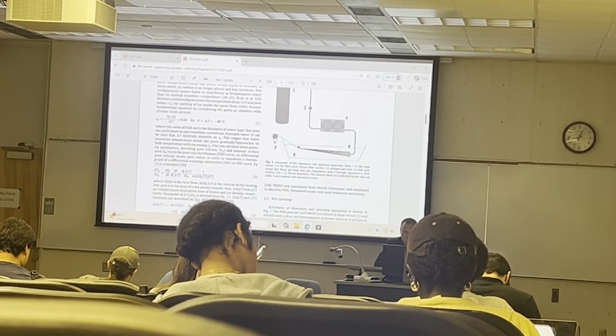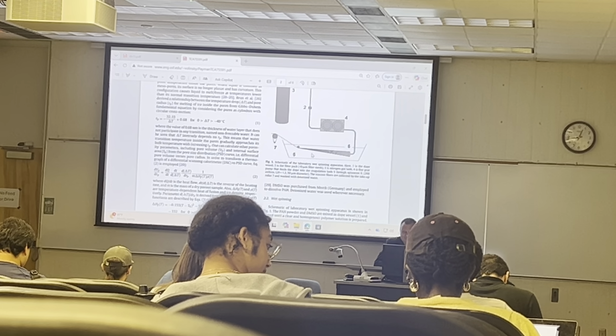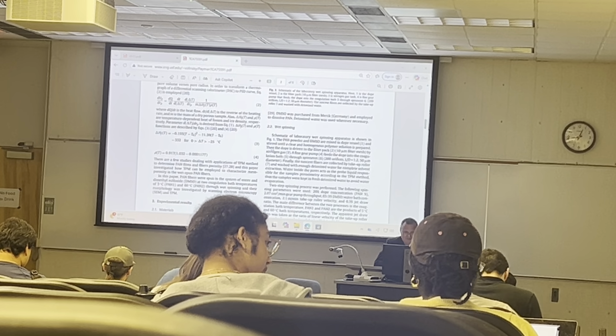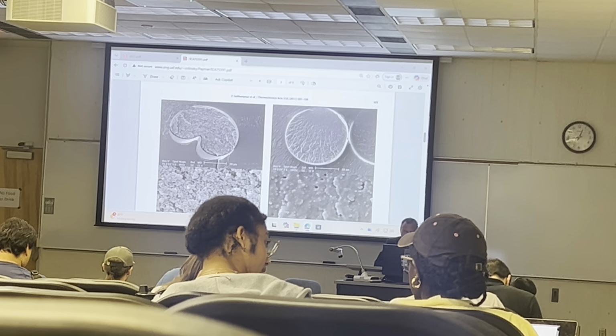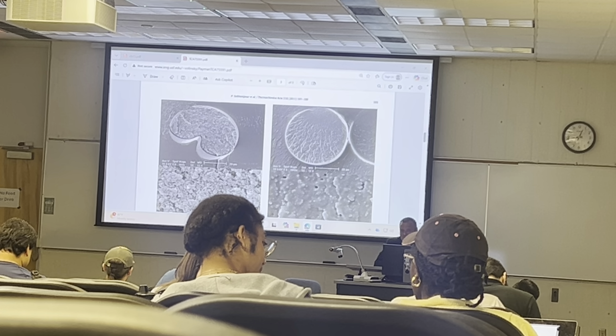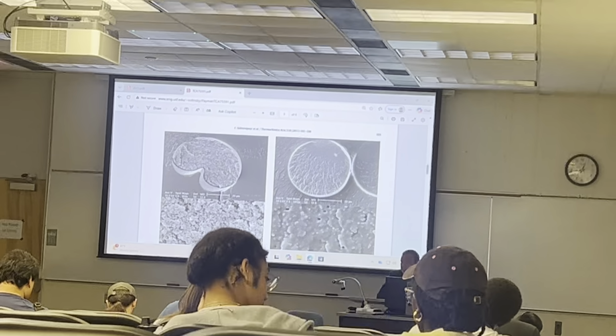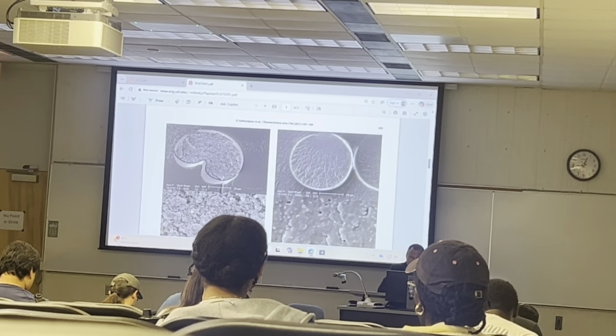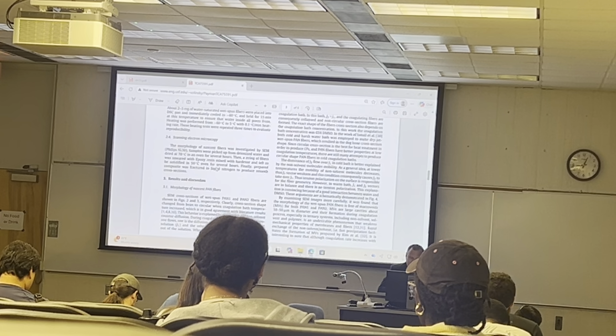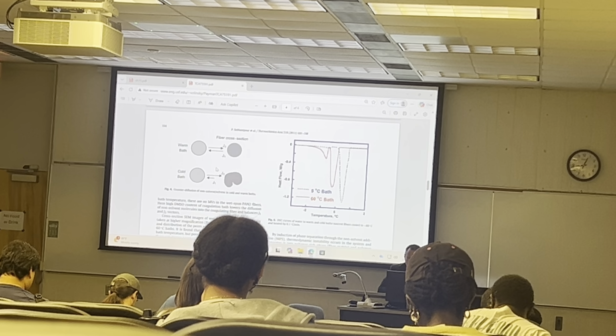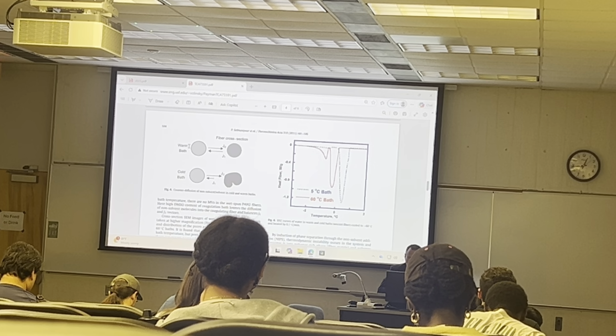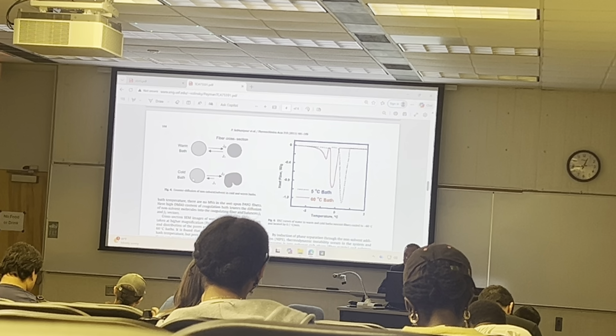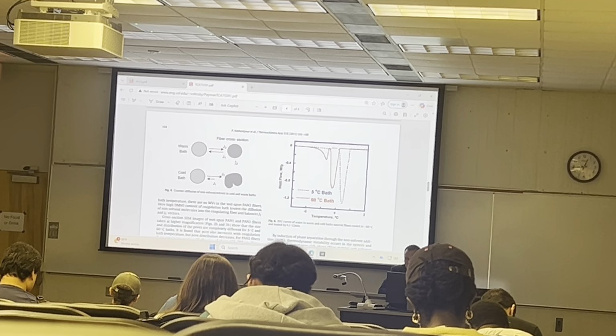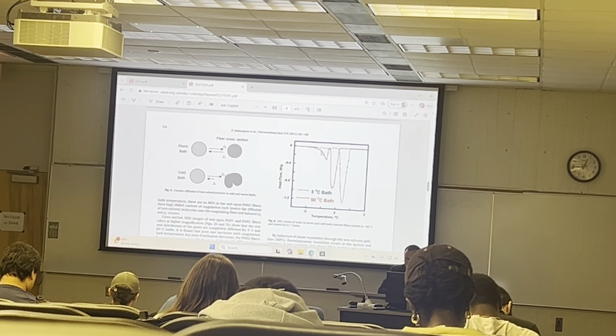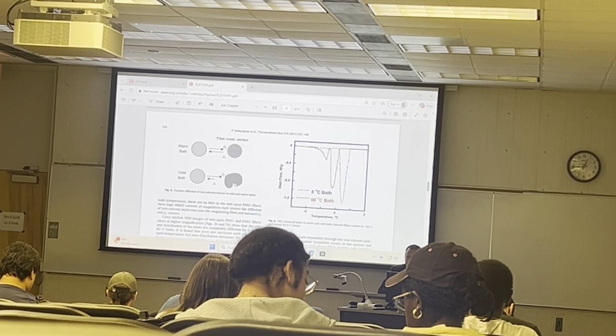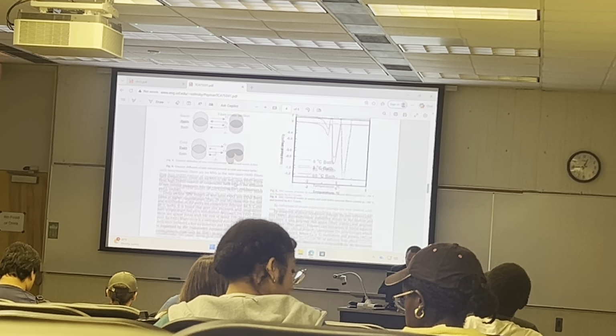here is a process of getting the fiber from the melt. And then the fiber gets, through wet spinning, this is the cross section of the fiber. The idea is that the fiber has to have a cylindrical shape with a circular cross section, but sometimes it goes into this bean shape like this, and it's a defect. The difference in the processing was in the warm bath versus the cold bath. So the fiber goes into liquid, into water. All right, and apparently it affects the percolation threshold. That's the scientific term for that.